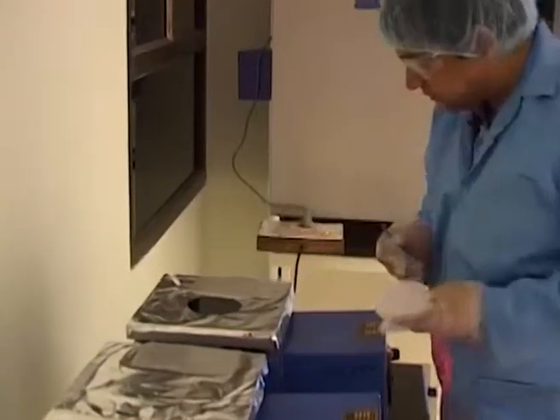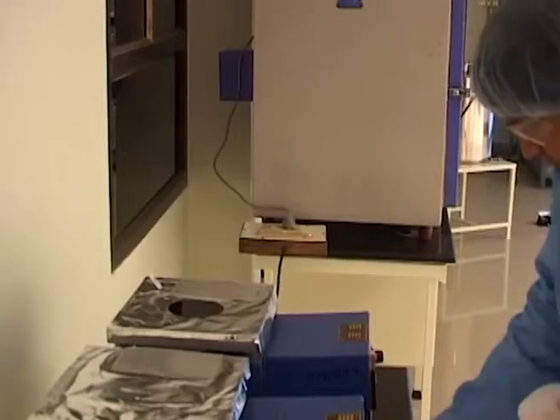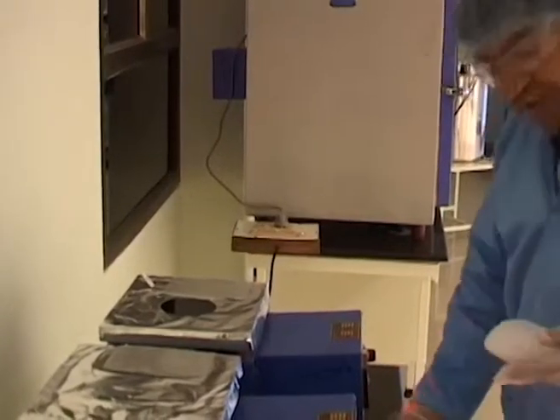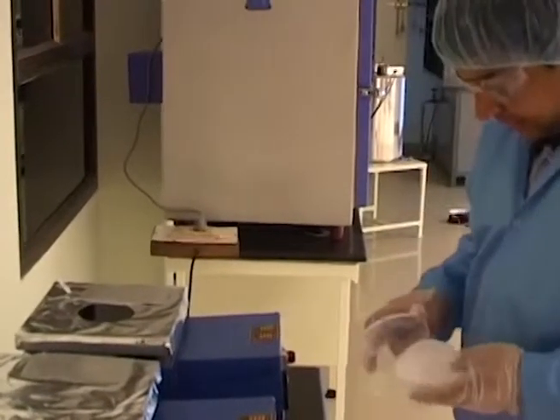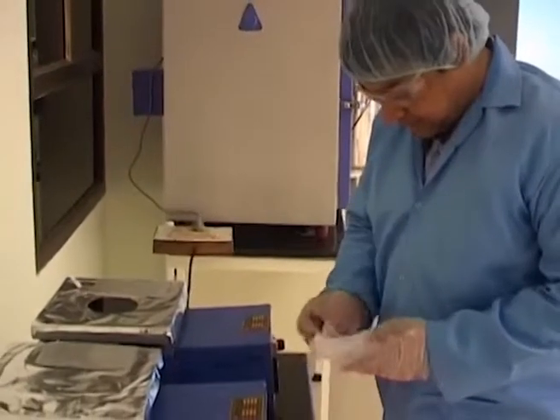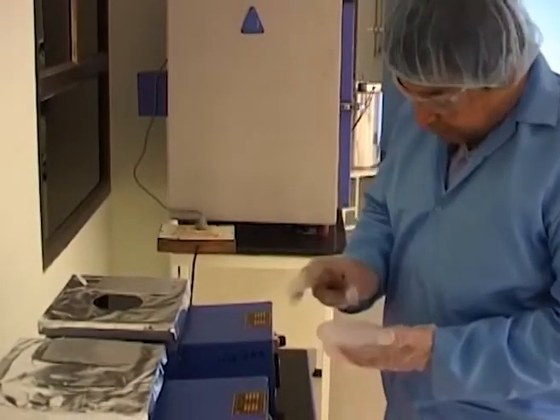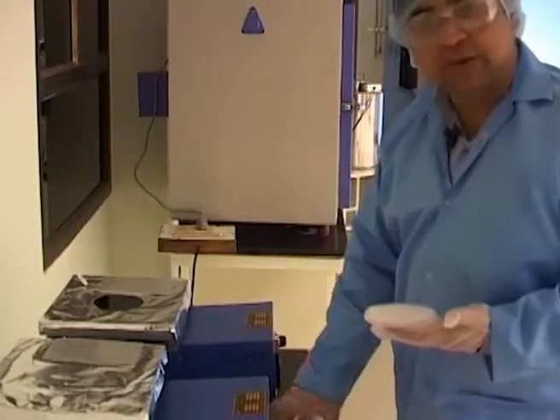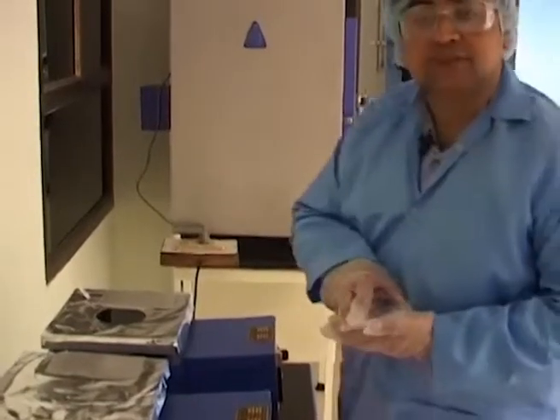So we pick it up from its location, and put it over this plate which has been set to a temperature of 95 degrees Celsius. We start the stopwatch and set it to about 6 minutes. So the idea is that after 6 minutes, as we hear the second alarm, we should be able to pick this up and then again let it equilibrate back to room temperature before the exposure process.